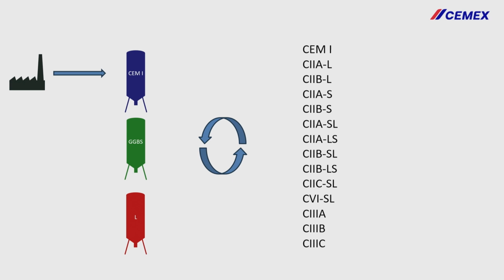Yeah, you can start using your limestone fines for rheology reasons, to control your bleed, to improve surface finish, and you can add up to 20% limestone fines and call it part of the cementitious, but you can put in another 3, 4, 5, 10% to improve the rheology of your concrete.